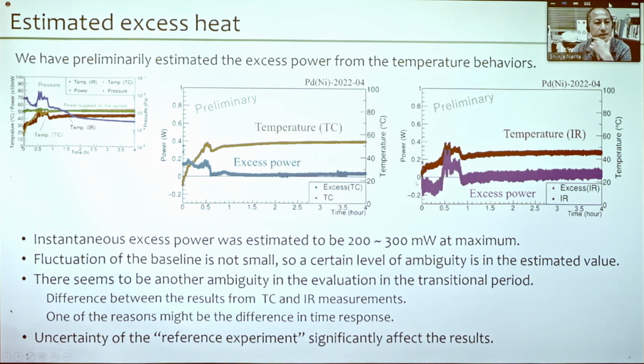Okay, so now this is the estimated excess power, 5 minutes. And this middle one is the excess power estimated by the thermocouple measurement, and this right one is from the IR, infrared thermometer measurements. So now we can see the instantaneous excess power was estimated to be 0.2 or 0.3 watts, 200 to 300 milliwatts, here and here at maximum.